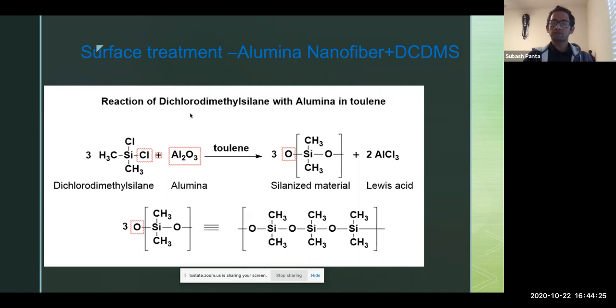Silane treatment of alumina nanofiber. In silane treatment, dichlorodimethylsilane is treated with alumina nanofiber in 50 ml of toluene. After we obtain the silanized alumina nanofiber, we dry it in an oven and disperse the alumina nanofiber through a roll mill.